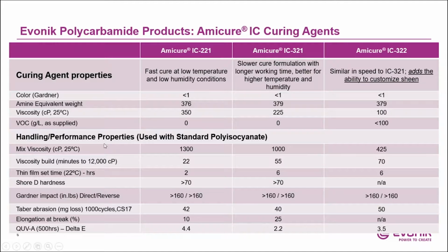Okay, so now let's get into the handling and performance properties, and that's when used with the standard polyisocyanate. So these are properties after you mix in with the polyisocyanate. So mixed viscosity, once you blend them together, you start out with about 1300. So they're all pretty much, IC221 and 321 are in the 1000 centipoise range, 322 being a little lower in terms of mixed viscosity. So these are all in the range where you can still apply it without need for solvent. And if you use a lower viscosity grade polyisocyanate, you can even get lower mixed viscosity.